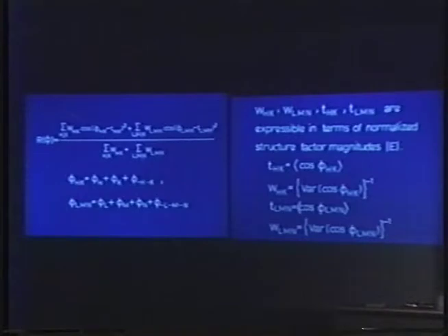So what we have here is a function of structure invariance, and because the structure invariants are themselves expressed in terms of individual phases, we have defined implicitly a function of the individual phases themselves. The minimal principle states very simply that the correct values of the structure invariants are those which minimize this function of structure invariance, subject to the constraints imposed by the identities which the structure invariants must satisfy.